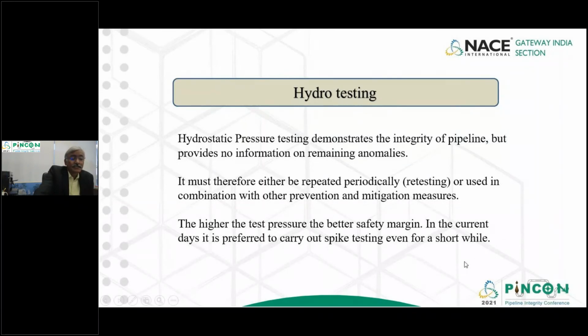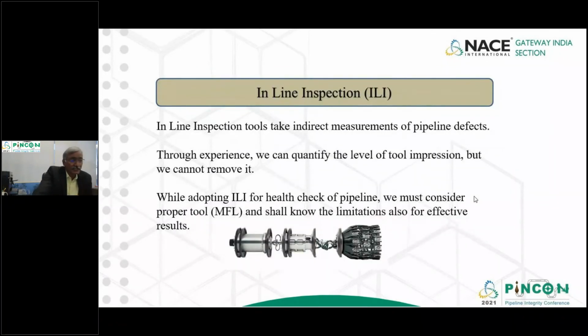And in the current days, it is preferred to do the spike test even for a short while. You can do it in a few minutes, but you do it at the maximum pressure available, 90% SMYS, or even it can go 95% or even 100%, subject to the agreement you have with the line pipe manufacturers. So inline inspection tools take indirect measurements of the pipeline defects, because basically it is done through the